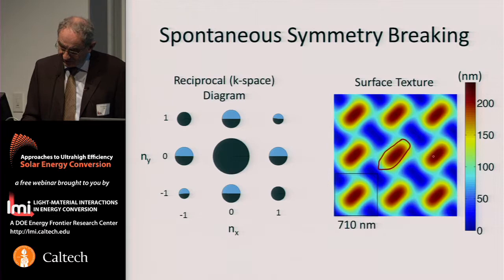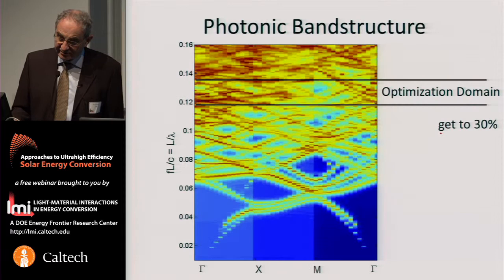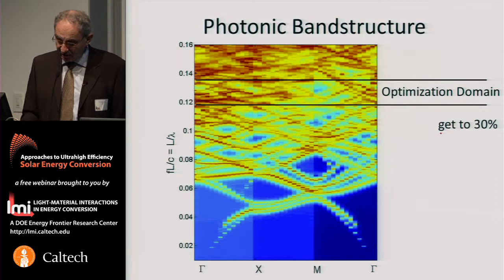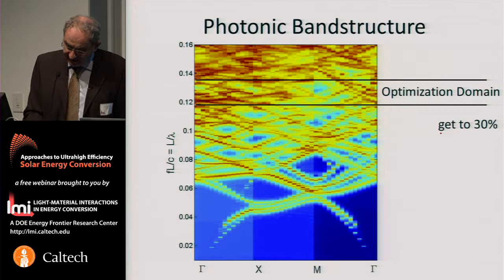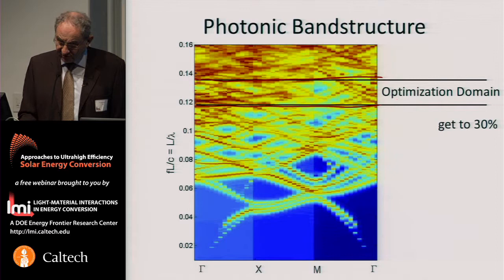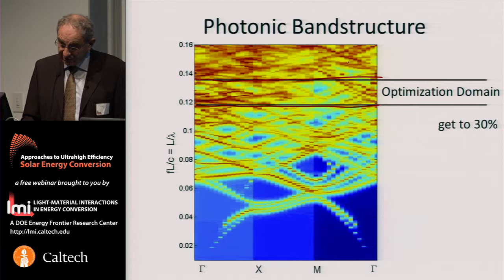is even more asymmetrical. And what is happening is that this mathematical optimization is forcing you into a type of photonic band structure. And this texture, you can imagine that texture being described by periodic boundary conditions, which are often used, in which case you'd say, well, you end up with a two-dimensional photonic crystal. But in fact, it's pushing you up into the very high-lying bands of the photonic crystal, where you have very random trajectories, random bands, and in fact that is exactly what nature is telling you to do. And you end up with a very asymmetrical symmetry breaking, which gives you the strongest optical absorption. So that's a project that is being conducted by Vidya Ganapati, who is part of our